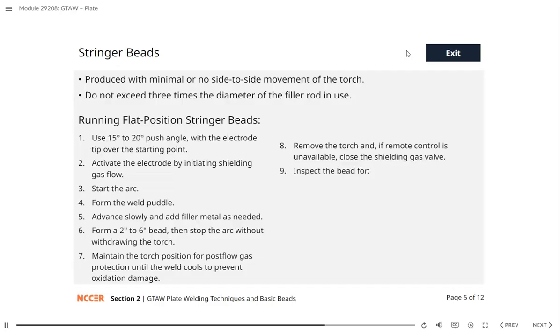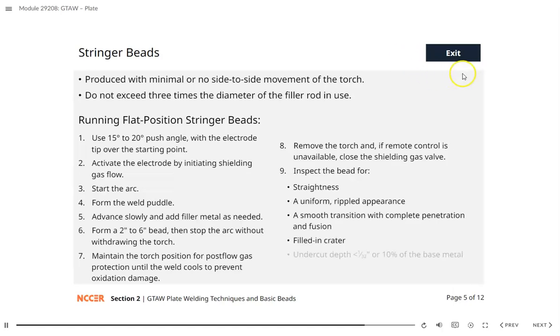Step 9. Inspect the bead for straightness, a uniform rippled appearance, a smooth transition with complete penetration and fusion at the toes, a filled-in crater, and undercut less than 1/32 of an inch deep, or 10% of the base metal thickness. Also check that the bead has no overlap, pinholes, cracks, or excessive porosity.